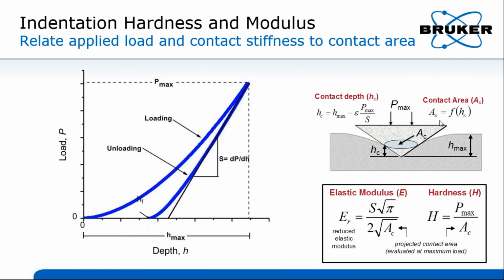Once we know the contact depth, we need to know more about the tip geometry. We need a function that gives information about the indenter projected area for each depth of penetration. Once the projected contact area A sub C is determined, the hardness is simply the maximum load P max divided by the contact area. On the other hand, the reduced modulus Er can also be calculated using the unloading slope S and the projected contact area.